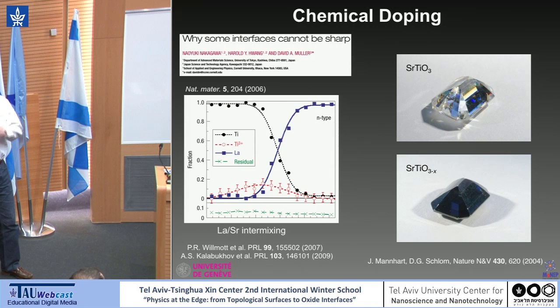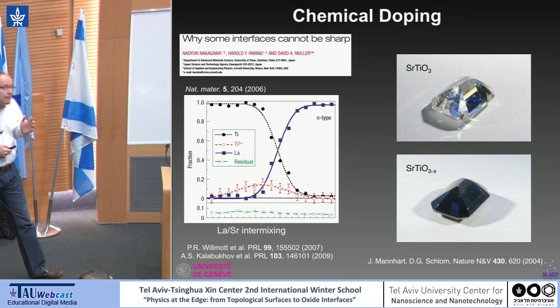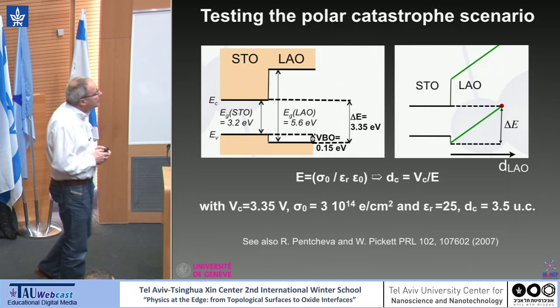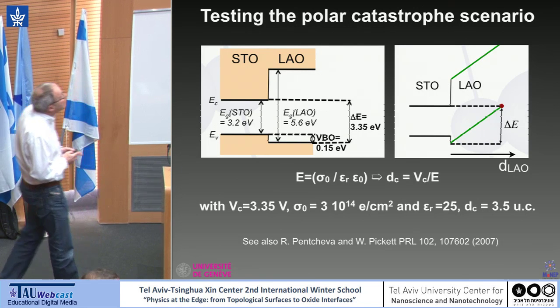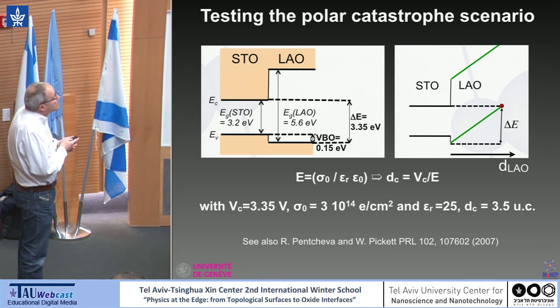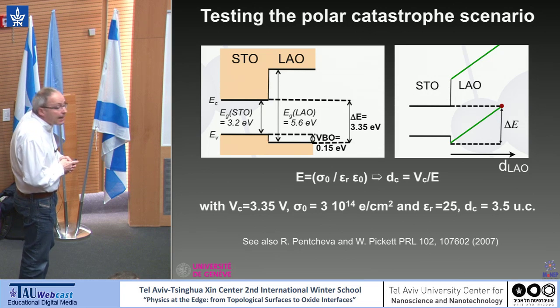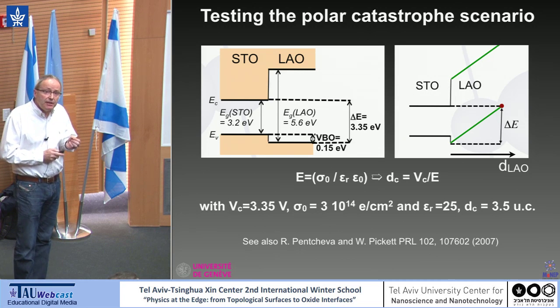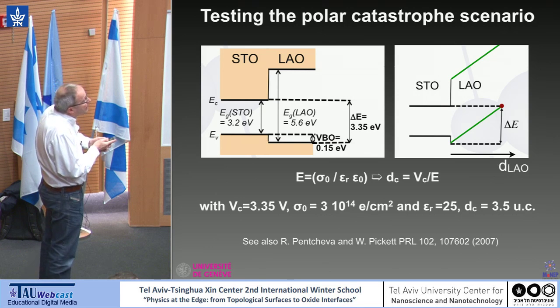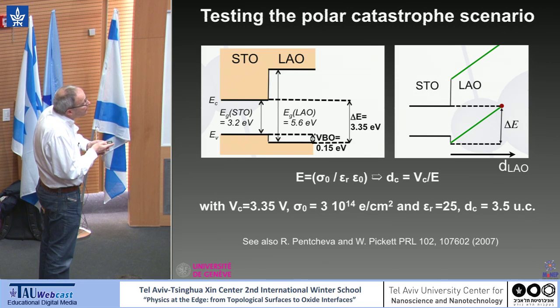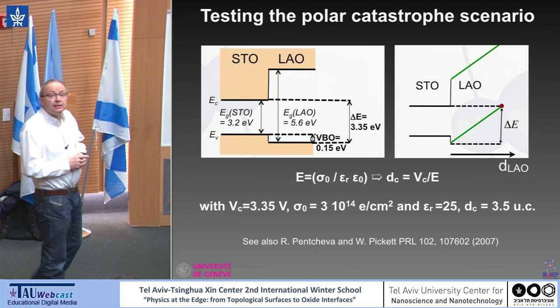Okay, let me discuss now a bit in more detail this interfacial structure. This is the band structure at the interface. Strontium titanate has a 3.2 eV band gap, lanthanum aluminate 5.6 eV. There is a small shift here. And now, because you have this electric field in lanthanum aluminate, you have band bending. And you see that the top of the valence band of LaO is going up in energy with the thickness of lanthanum aluminate.